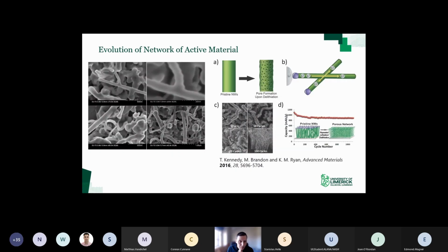Okay, so we put forward a theory of what is causing this deformation, and like I said, it's this pore formation coupled with something known as electrochemically assisted welding. So not only are you getting pore formation, which forms the ligaments, but the ligaments, if they're in contact with each other, can weld to each other as well. That's important because it gives you this interconnected network.